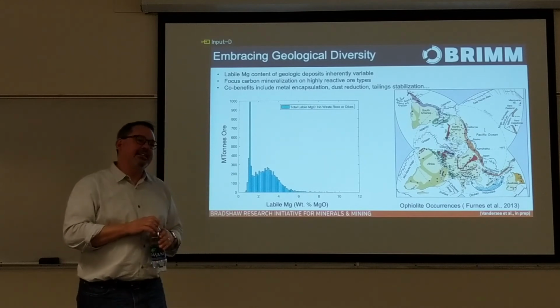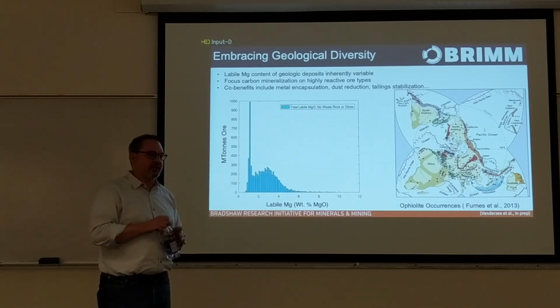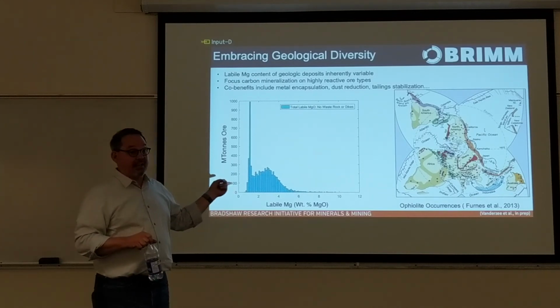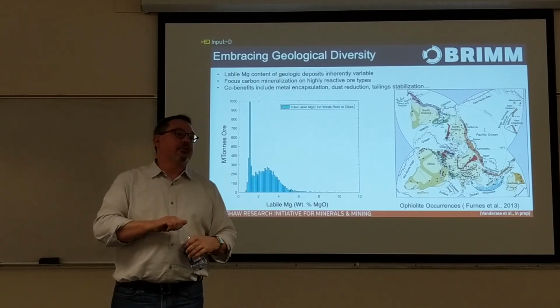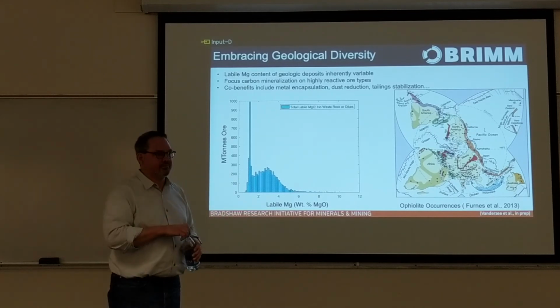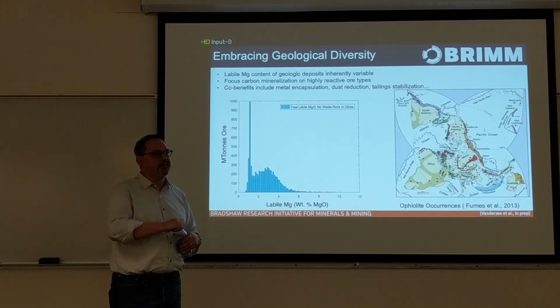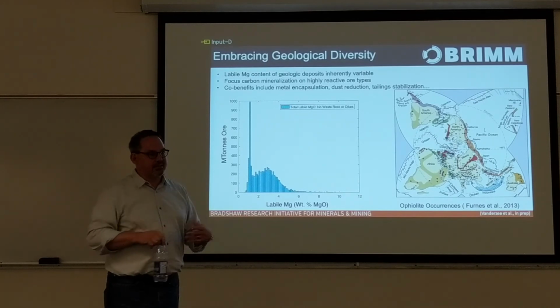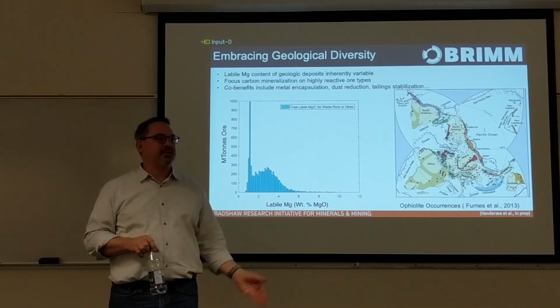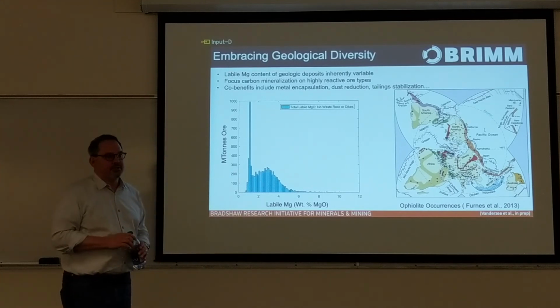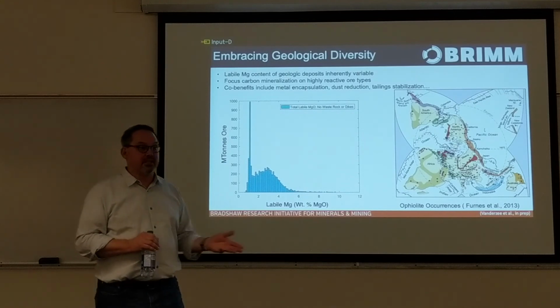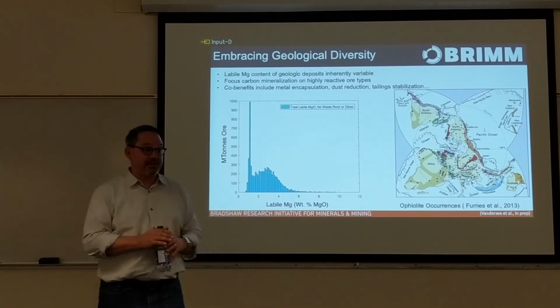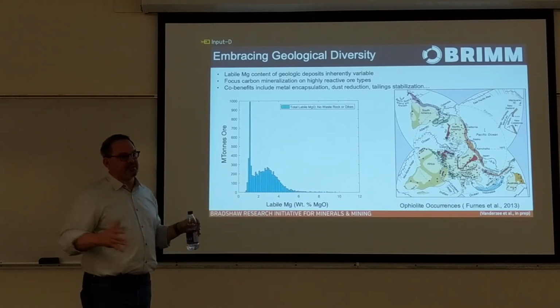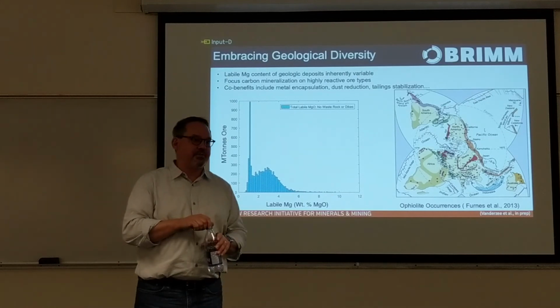The key for clays is that here we're doing cation extraction, whereas for clays you're doing cation exchange. So you need to put a cation in. Hopefully, you can put in a cation that doesn't like carbonate and liberate one that does. And then, if you're getting that by adding potassium chloride, you've got to put the chlorine somewhere else because you don't want to make magnesium chloride. So you also need to separate the anion from the cation when you precipitate.